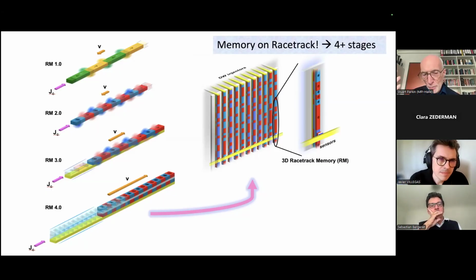In racetrack 3.0, we've introduced this yellow layer, which could be platinum or tungsten, or more recently, we've shown, using some very special L10 iridium based alloy materials, we can achieve conversion efficiencies of charge to spin of more than one, in fact, up to three, we believe. That means every electron will generate three spin polarized electrons. This enables us to move these domain walls much more efficiently, and in this case, the velocities that are possible are about 300 meters per second.